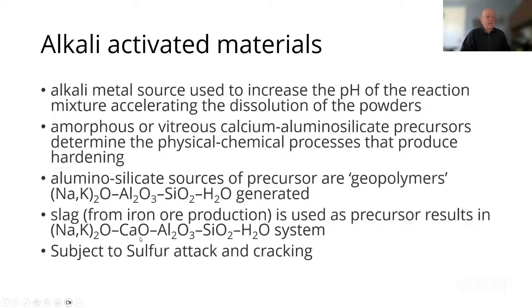But then some of these materials are also subject to sulfur attacks. So imagine now you use some material that has a lot of alumina in it. Well, that actually exposes that material to a sulfur attack that will result in cracking. So there have to be, in addition to substituting alternative raw materials, often ways of including other additives to avoid these other reactions.